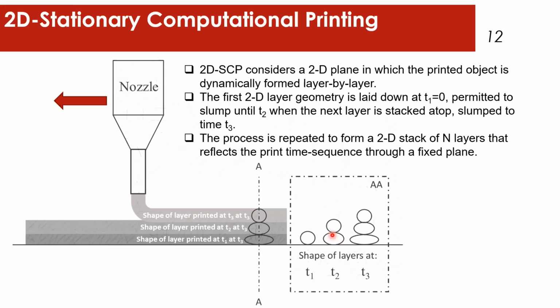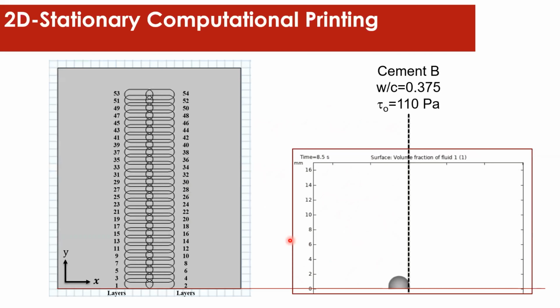At time T2, the second layer will deposit such that at T3 minus T2, not only will the upper layer slump on itself, but the bottom layer will slump under the weight of the upper layer. At time T3, the printer passes again and deposits the third layer, and so on, and it will continue to. Now I have prepared a video that shows how this happens computationally. So what I'm not doing here is piling up a bunch of layers at time t equals 0 and then slumping all of them together. That's not what this is.